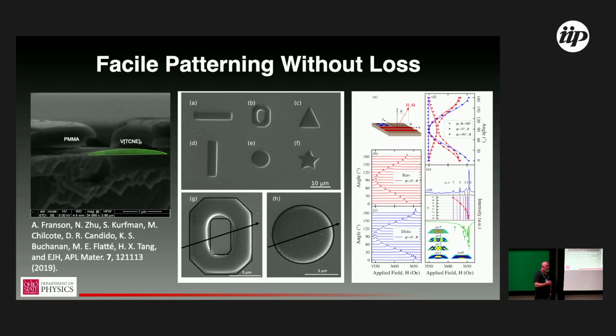In particular, coming back to the CVD synthesis, it's such a gentle process, low temperature, modest pressure. We can use e-beam lithography to pattern and lift off the deposition. So that means we can form arbitrary structures. But interestingly, the growth dynamics are not UHV direct beam deposition, but rather convection flow driven by the gas dynamics, and effectively you form a vortex at the edges of your pattern where the diameter of the vortex is basically the height of your resist layer, and that leads to this lens-like cross-section.